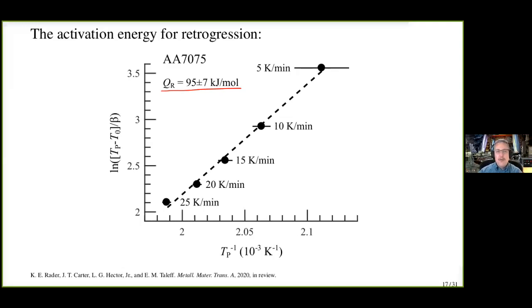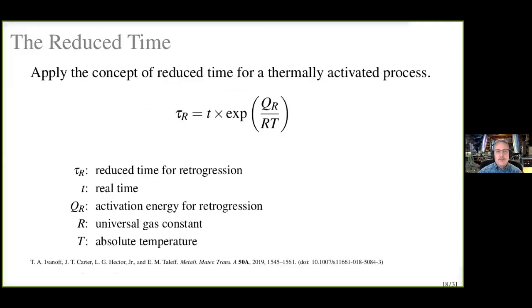Now, what that gives us the power to do is to define something called reduced time. So we can take that activation energy for retrogression and put it into just the 1 over our Arrhenius relationship here. We multiply that times the time for retrogression, and we define something called the reduced time for retrogression right here. So it allows us to compensate time with the temperature we're actually retrogressing at. So by combining time and temperature, we now get a predictive capability. So let me show you how we use that predictive capability.